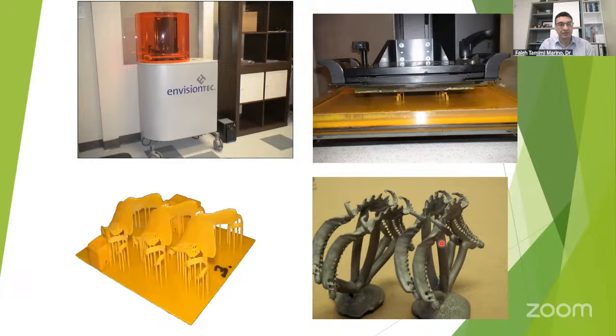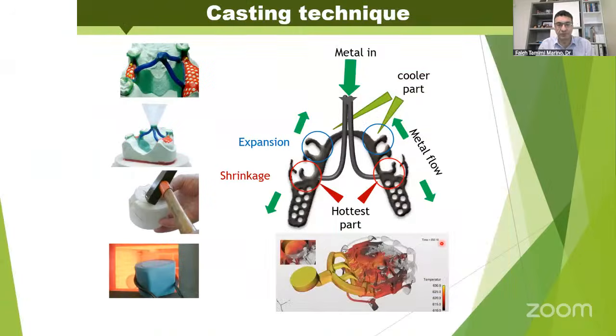However, the company working on this, 3D RPD, very quickly found that you still have issues with these frameworks, because they are cast. Metal casting is a method that has been around, I think, for 5,000 years. It's a very old technique that is very good, but it's not ideal, because when you're injecting very hot metal into the investment material, many things could go wrong.